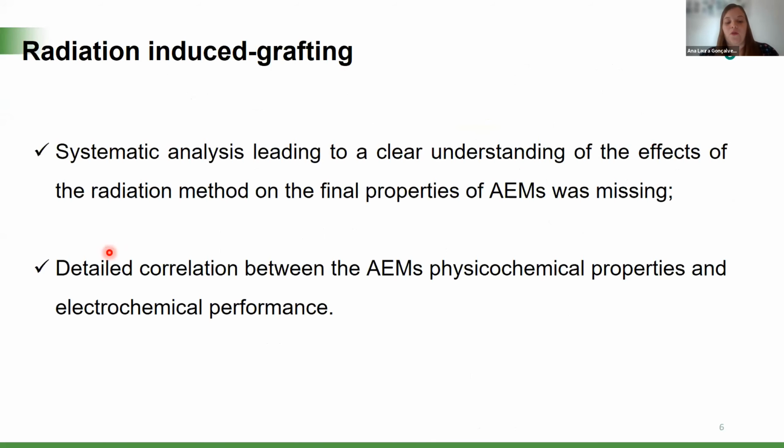Despite several reports on these methods in the literature, there was no systematic analysis leading to a clear understanding of the effects of the radiation method on the final properties of the anion exchange membranes. So we did a systematic analysis of the radiation-grafted LDPE membranes produced by the simultaneous method and the pre-irradiation method. And we provided a detailed correlation between physicochemical properties and electrochemical performance.